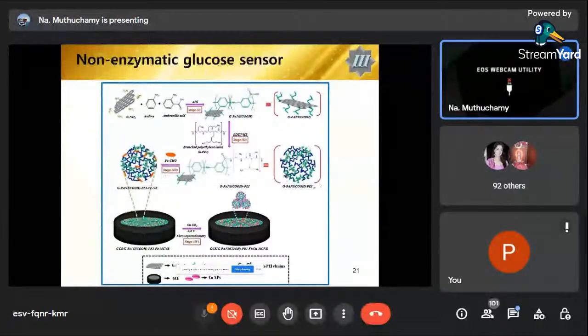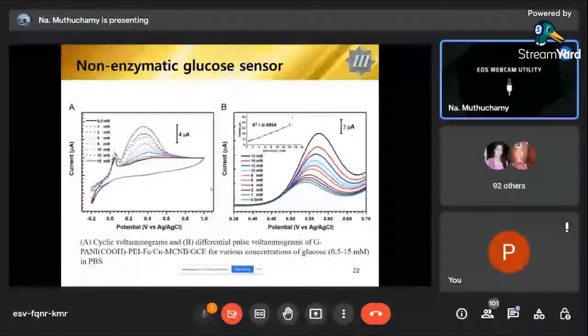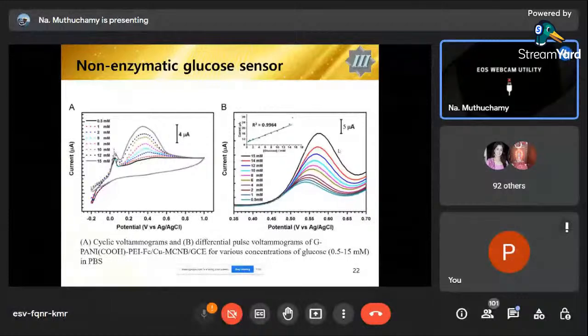To confirm the biosensing probe, first we performed CV. You can see that when we increase the concentration of the glucose, we always get the oxidation of the glucose at 0.4 volt. To confirm exactly the sensing potential, we performed DPV. You can see that when we increase the glucose concentration from 0.5 millimolar to 15 millimolar, the current increased by around 28 microamp. Also the potential is shifting towards the positive region. So it makes sense for the real application.